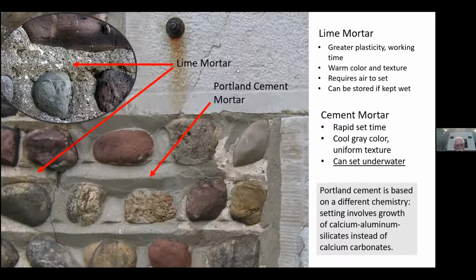And so this picture is showing a piece of a cobblestone building. I spent 30-some years living in the Finger Lakes of upstate New York, and one of their regional architectures there is cobblestone construction, where you have these buildings which are constructed out of rounded glacial cobbles. So there are these nicely rounded stones through here, which were originally held in with a matrix of lime mortar. And the lime mortar was used in these buildings because lime mortar has greater plasticity and working time. So when you're going to do all this fine joint work, such as you see back through here, it allowed for that to happen. And it has a very warm color and texture to it.